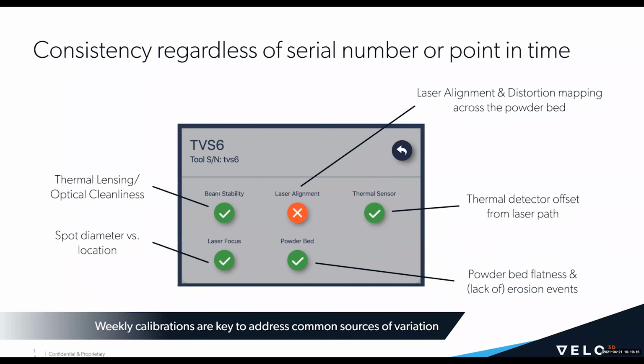So the first one is beam stability. This is basically verifying that the optical train is clean, because if there is debris in the optical train, then the spot will move as the optical train heats up. The debris will heat up and cause variation with respect to time and temperature. So we verify for that with beam stability.